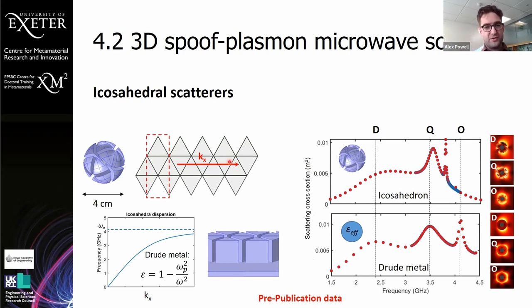The way we compare if this matches an effective medium approximation is to unwrap the whole structure into a net and look along the x-axis to begin with, because looking along here most reliably replicates what we see in this sphere. And then we can look at the dispersion relation, and from the asymptotic frequency, we can determine the effective plasma frequency of this structure. And then from that, we can determine an effective permittivity for this. And if we model just a sphere of this effective permittivity, we can see that it matches pretty well for the first couple of modes.